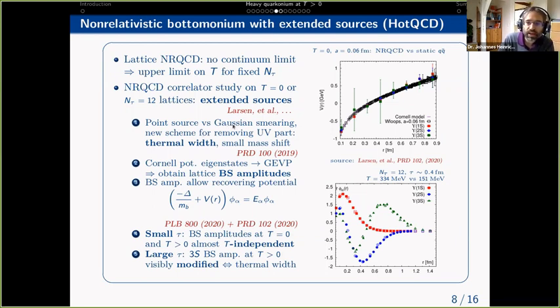What was found in this case is that once one uses a new scheme to remove the ultraviolet part of the correlation function, by estimating the ultraviolet part of the finite temperature correlation function as being roughly the same as at zero temperature, you could then get a very, very mild time dependence of the correlation function, or the so-called effective mass, that indicated that the thermal width of these bottomonia is large and the mass shift of the bottomonia is small.